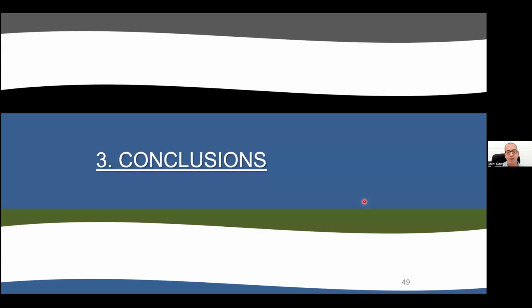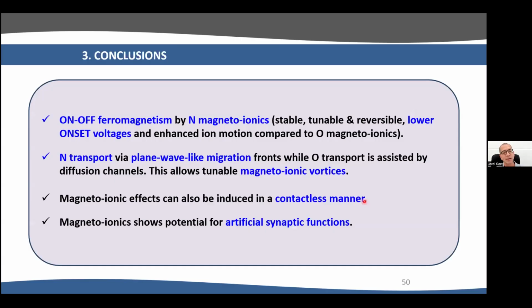Okay, I would like now to point out some conclusions. I have shown you that we can induce on and off switching of ferromagnetism by nitrogen magnetoionics, that the effect is faster than for oxygen. We need lower onset voltages. There is a particularity of this material, this planar wave front, that at the beginning was a mere scientific curiosity, but later on we could use this to induce formation of magnetoionic vortices, or what we call vortions.